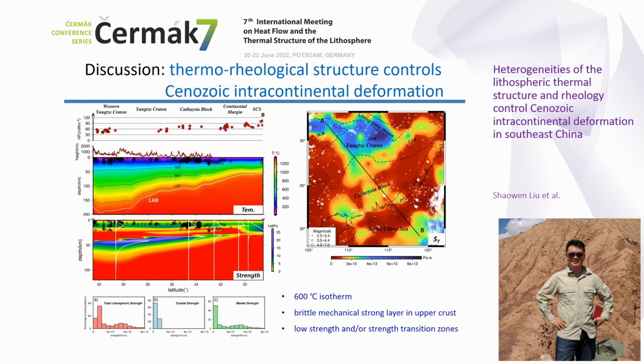In addition, the lithospheric thermorheological structure controls the distribution of the intraplate earthquakes. In the temperature profile from continental interior to the ocean, we can find that the seismicity is limited within the 600 degree isotherm. In the strength profile, we find the seismicity almost distributed in brittle mechanically strong layers in the upper crust. Besides, the seismicity aggregates in low strength and strength transition zones, like the middle northern Yangtze craton. This kind of seismicity pattern has also been observed in other continents, like North America and Australia.